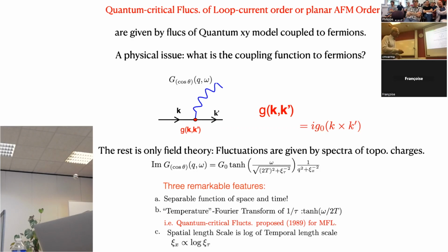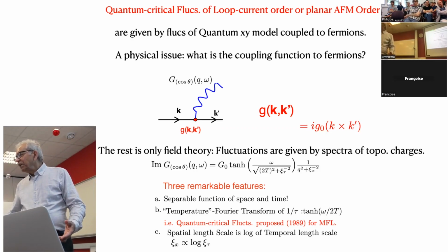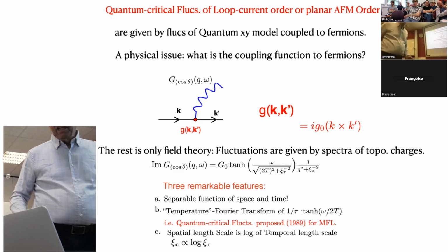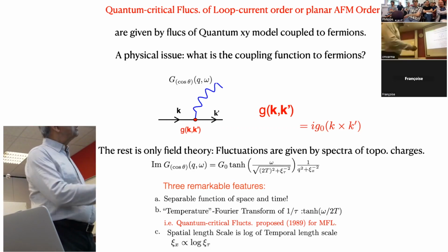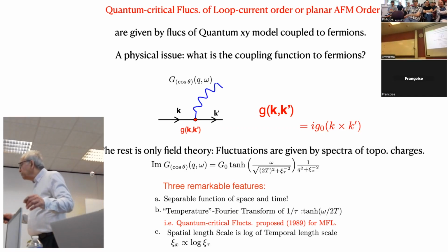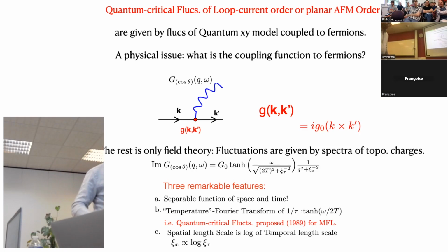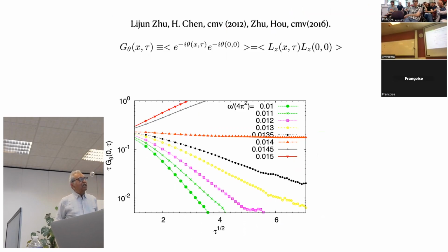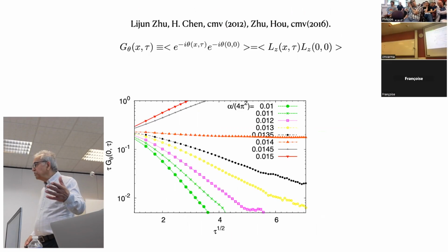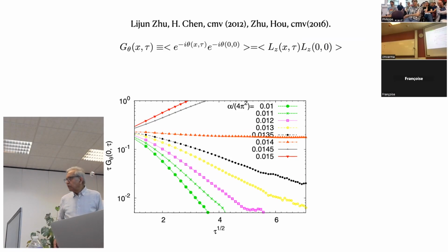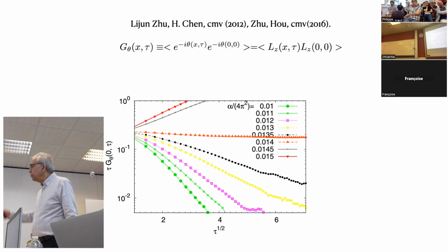I'm going to show you what the fluctuation spectrum is, and it's by an experiment. We can derive it by some renormalization group technique, but it's much easier to show the result by taking this model with this kind of coupling to the fermions, integrating over the fermion, generating an effective new coupling, adding it to that of the XY model, and doing Monte Carlo calculation on it. Okay? So this thing has no sign problem, and this is Monte Carlo in the space of three parameters: the kinetic energy of the fermions, kinetic energy of the rotators, the interaction between the rotors, both normalized to the upper cutoff tau sub c, and the parameter alpha coupling it to fermion. And in the space of these three parameters, there's a two-dimensional surface at which the critical exponents are identical.